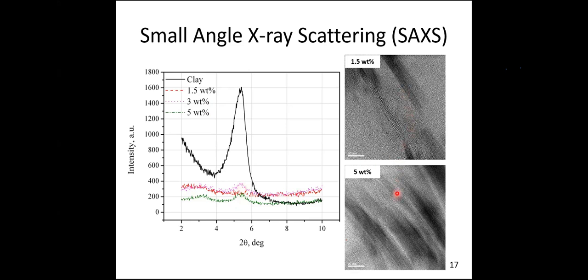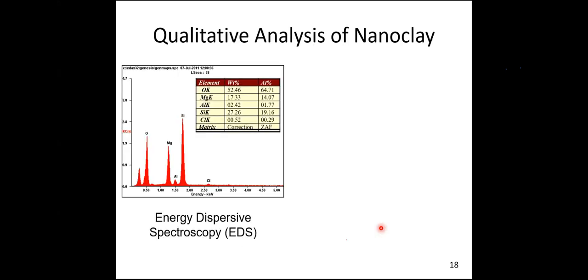So this is a TEM, again this is the micrograph from transmission electron microscopy. If you see for 1.5 wt%, you could see it is dispersed nicely, wherein in the higher clay loading, you can see it is agglomerated. So this is what we could see from the XRD and transmission electron microscopy, TEM.